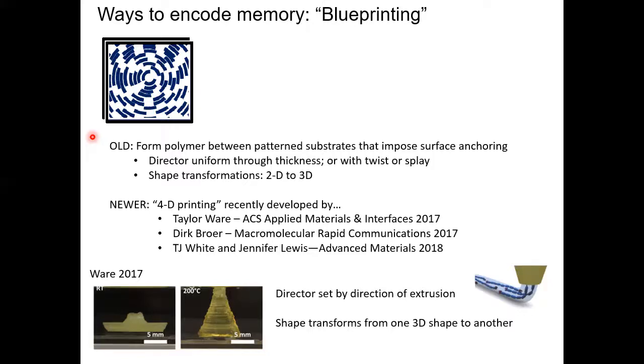That sounds even cooler than 3D printing, right? So 4D printing, the first paper came out in 2017, is the process of essentially building an object with a 3D printer. And what makes it 4D is that it changes shape with time. For instance, it might change shape on heating or when you shine light on it or some other way. This picture actually came from the work by Tim White and Jennifer Lewis. If you remember this morning when you put toothpaste on your toothbrush, you're extruding the toothpaste. Imagine that when you're extruding the toothpaste, if there are any elongated molecules in it, they will align with the extrusion direction. And if you can cross-link them quickly before they drip off or flow very far, then you can trap that nematic order as written.